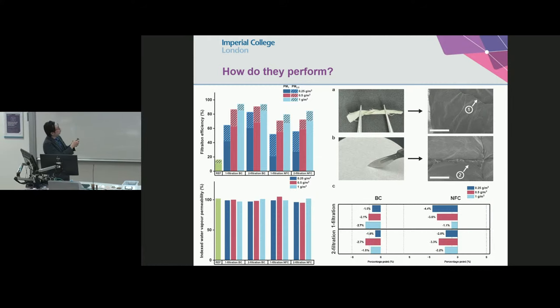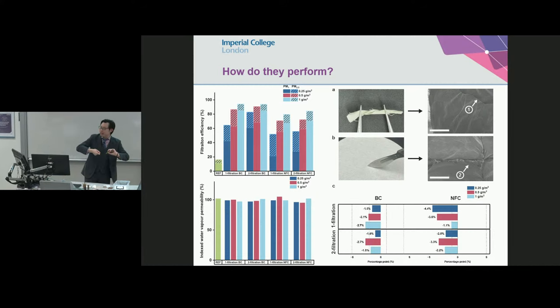The coating is actually quite robust as well. So we take our coated samples, we twist them, like how we use in real life. The coating is still there, just as a crease that you see. We cut them with a knife. Again, you see the cut, and the coating is still there as well. We wet them in water, we dry them out, thinking that that coating will fall off. It did not. It reduces the filtration efficiency by up to 2-3 percentage points, but that's it. The coating still stays there. Again, that's what you can achieve with cellulose, because you will form the hydrogen bonds, so it stays there quite stably.